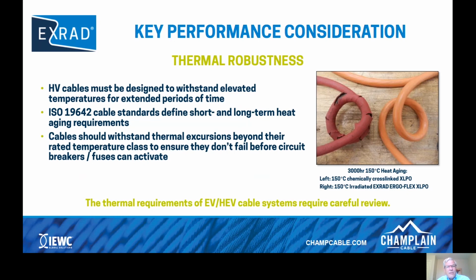Cables should withstand thermal excursions beyond the rated temperature to ensure they don't fail before the circuit breakers and fuses can activate. This is something some people are not aware of: fuses that are rated at 150 amps, let's say, for example, will take much higher amperage than that for a period of time before they blow. And the high voltage cable must be able to withstand those temperature excursions.